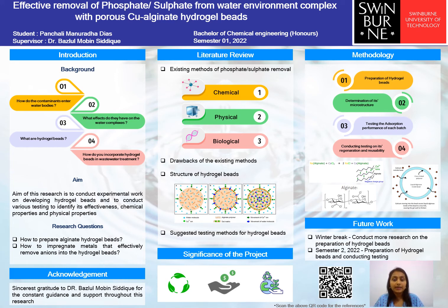preparation methods for the hydrogel beads, and mine would be modified like this. So the sodium alginate solution can be prepared, thanks to the technological maturity in this area, by purchasing the sodium alginate and dispersing it in 100 milliliters of deionized water, that is 1.5 grams, at 60 Celsius and 2 hours of continuous stirring. The stirring time is entirely dependent from research to research and component to component. So that is solution A. And solution B can be prepared by dissolving 16 grams of copper nitrate in 1000 milliliters of deionized water, and this solution A and B can be put together to prepare solution C.